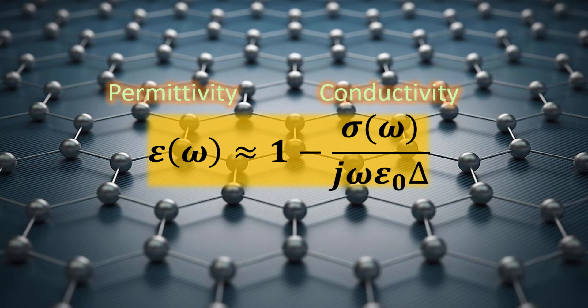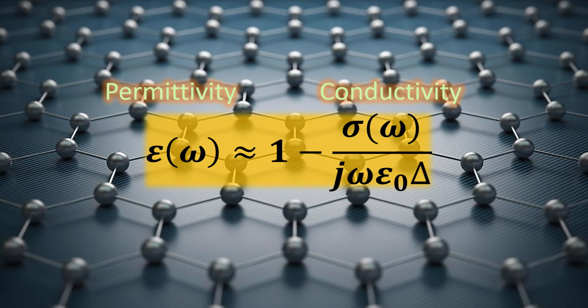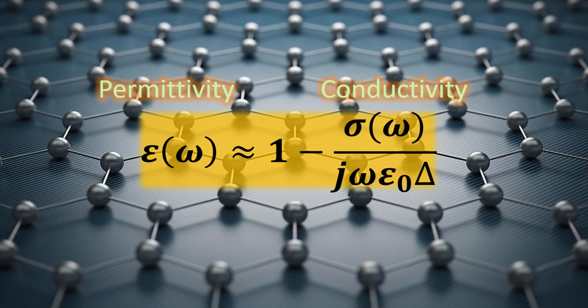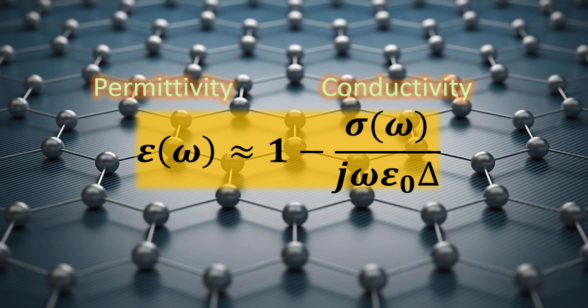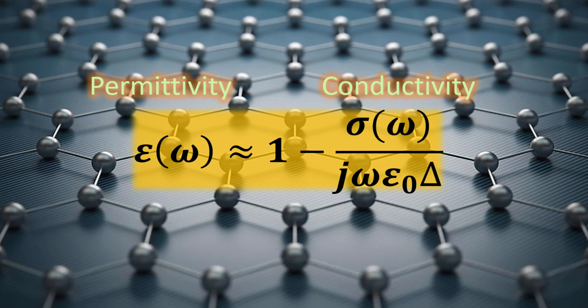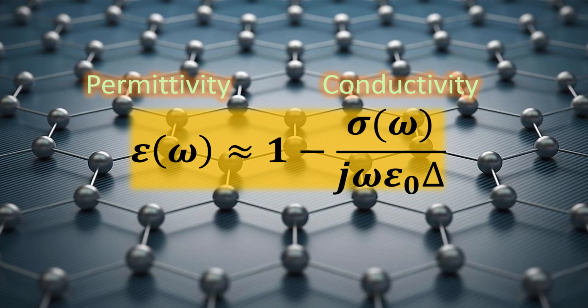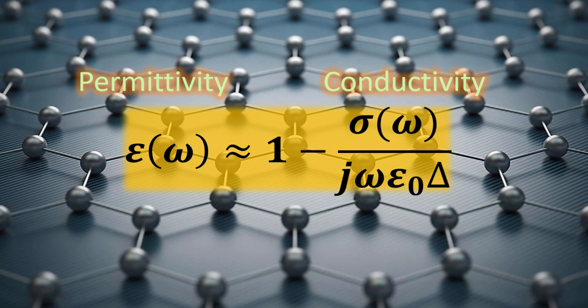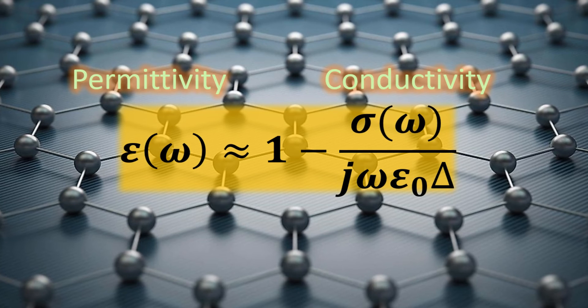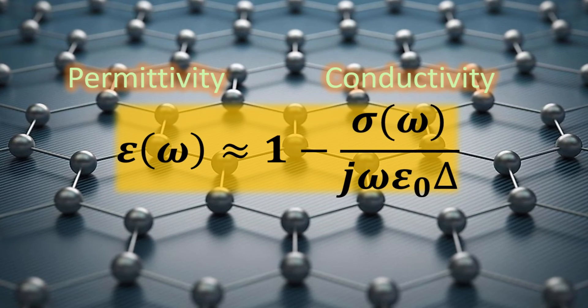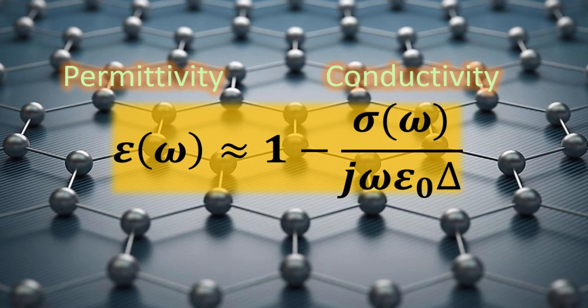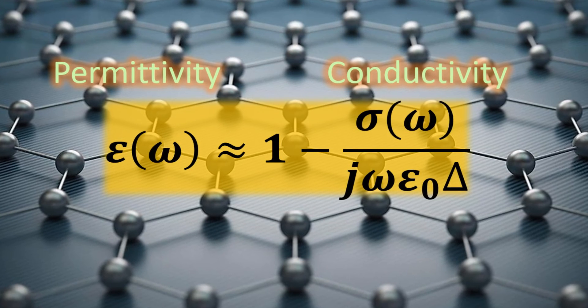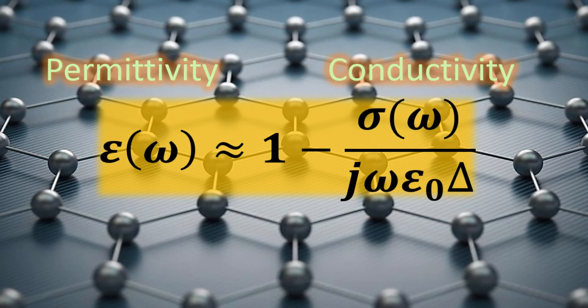As a side note, most viewers are probably more familiar with describing the material's optical constant in terms of the electric permittivity. However, since graphene is a 2D material instead of bulk, the electric conductivity is a more convenient quantity, allowing us to describe its electromagnetic response in terms of a surface current. Nevertheless, if one insists on ascribing graphene with a finite atomic thickness, delta, then one can also recast the optical conductivity in the form of an electric permittivity as shown.